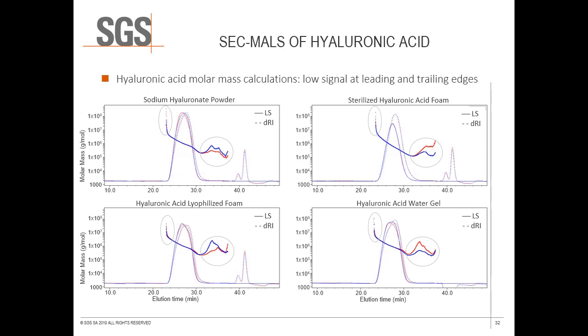Despite these differences, calculated molar masses are consistent for duplicate injections where signal is adequate. The viscous fingering effect here is slight, indicating that a minor decrease in polymer concentration and/or increase in mobile phase salt content may optimize this method.